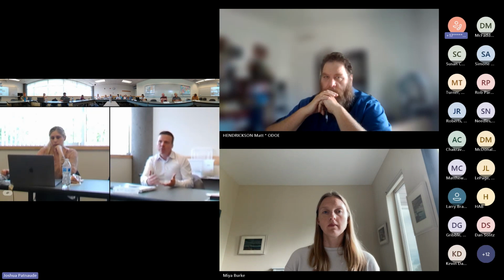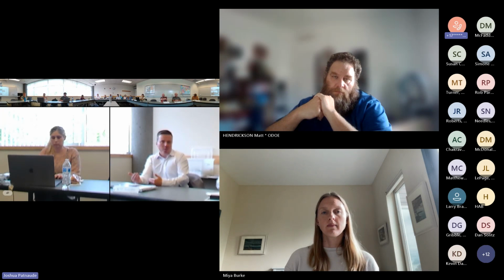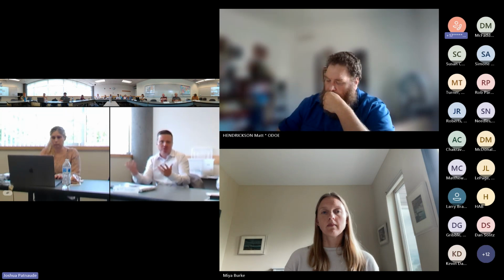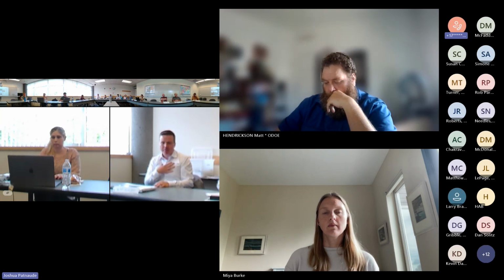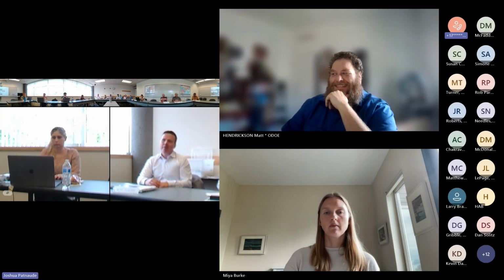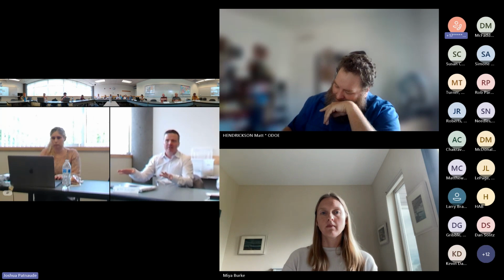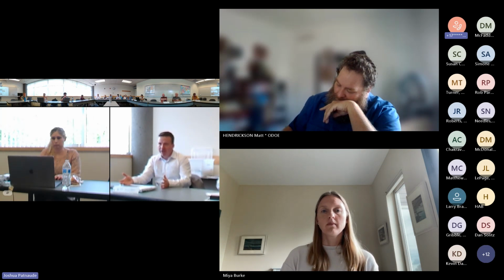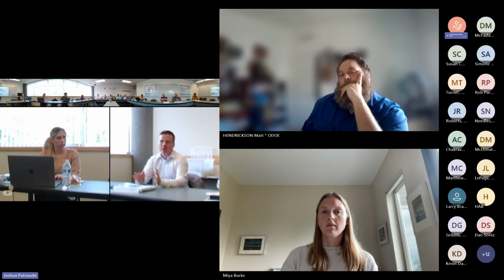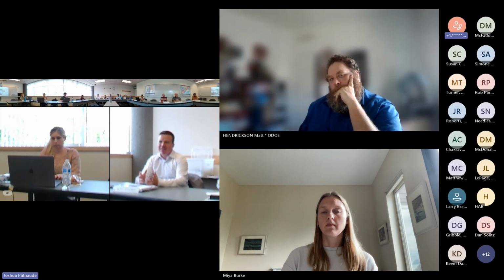So there's been research done at the Vitreous State Laboratory at Catholic University over the last 4 or 5 years. Weiliang Gong is a scientist there, where they have demonstrated a wide range of different grout formulations, a lot of things that look traditionally like geopolymers, and their ability to solidify simulated low activity waste. So we have more options in our toolbox when we go to screen things in the future. So from our end, yeah, if you take cement out, I think you're perfectly fine to call your resulting material a geopolymer. There are different classes of geopolymers where you don't have to alkali activate, but in our case, if you're using tank waste, it's an alkaline environment, it's going to be alkali activated. So depending on the ratio, there's a lot of terminology you could use, such as neutral salt activated slags or alkali activated slags, for what your waste form technically is.